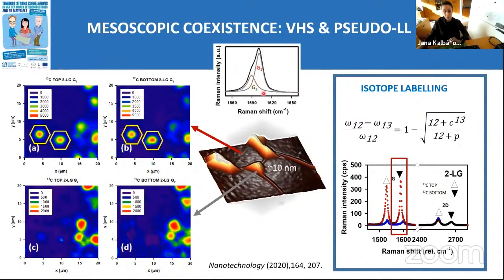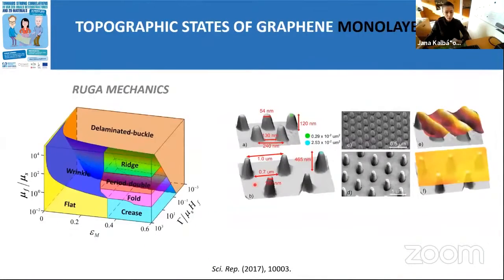And this is the band which typically corresponds to those corrugated features, because if we apply some advanced analysis, the deconvoluted strain and doping, we can really clearly say that the band coming here comes only from the graphene which is accommodated in the rugas, in the corrugations on the surface. So this is also very nice, that we can separately look at the bottom and top layer, and we can also disentangle contributions from the flat areas and the corrugated areas in the sample. So then I will skip to another example.